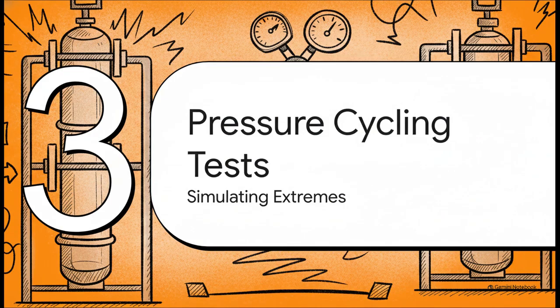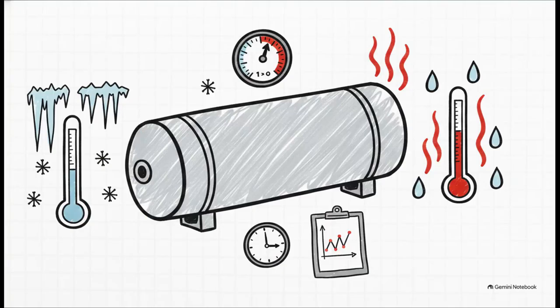Next up is Section 3, Enhanced Pressure Cycling Tests, where we simulate the extremes. All right, here we are talking about some serious thermal and pressure whiplash. First, they drop the ambient temperature down to minus 40 degrees Celsius, or even lower. Then they hydrostatically pressurize the cylinder to a staggering 260 bar, which, by the way, is over 3,700 psi.